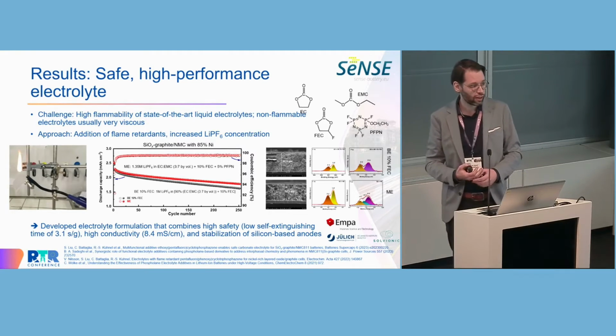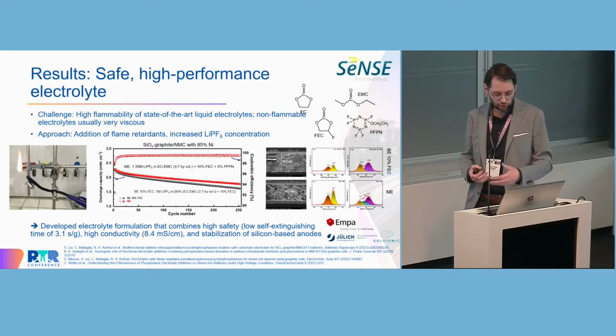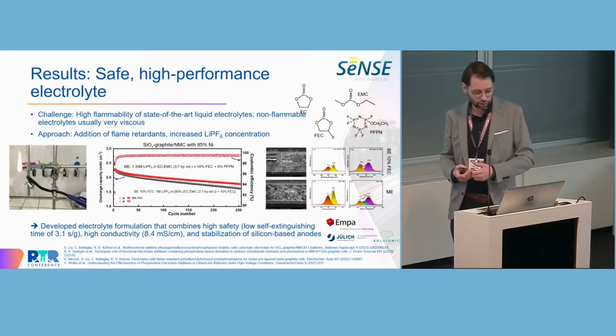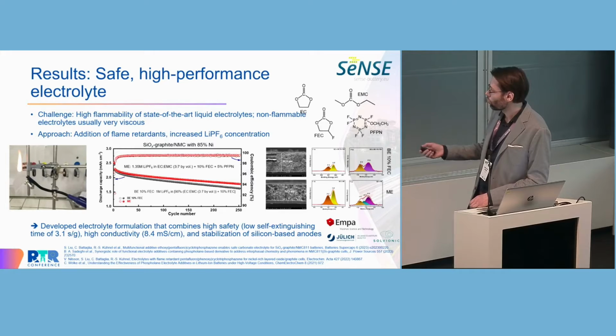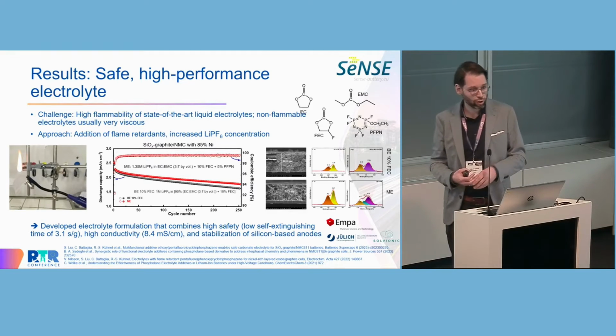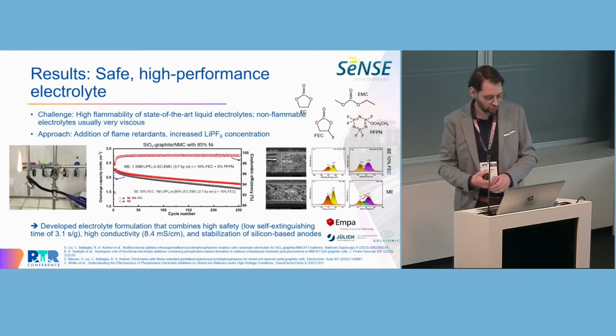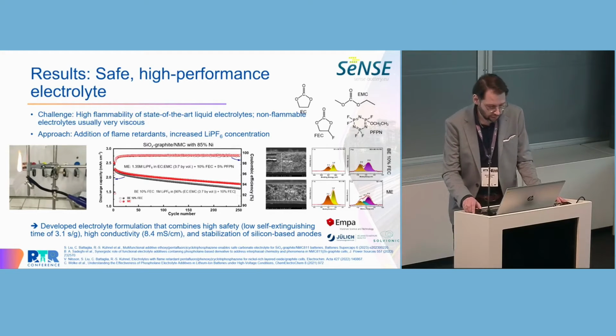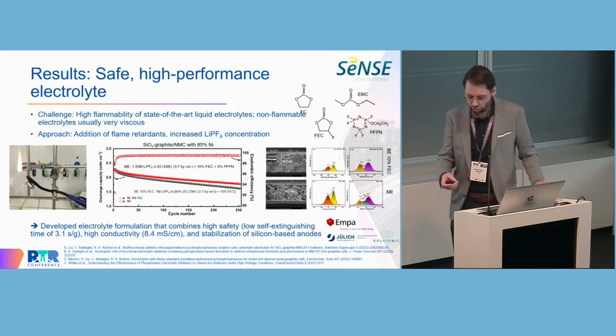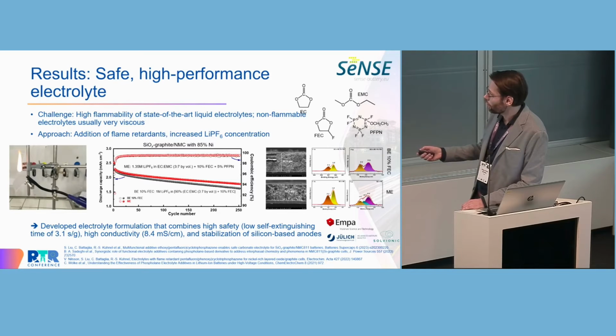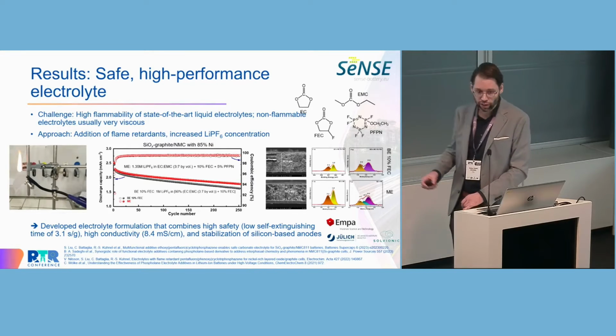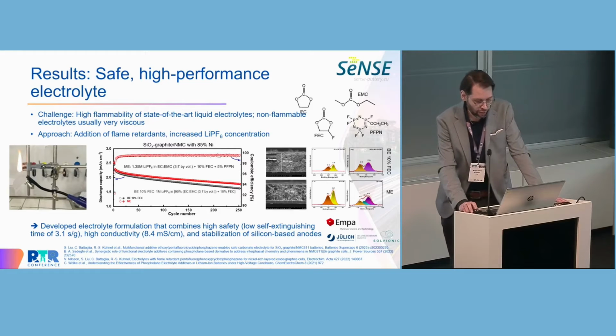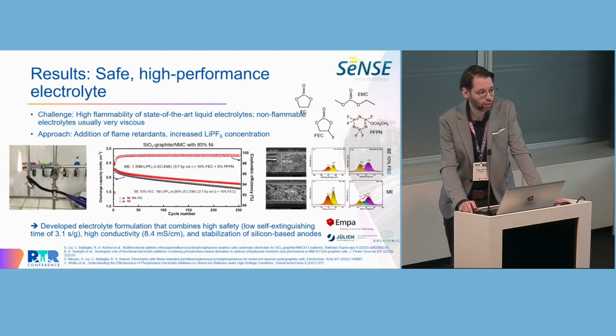We did some post-mortem analysis, and we found that the stabilization mainly takes place on the anode side. We saw that also the composition of this protective layer changes. It becomes richer in lithium fluoride, which is an important SEI component. And we also saw less volume expansion of the anode compared to the baseline electrolyte. And this electrolyte was then upscaled by our project partner Solvionic for the demonstrator pouch cells that we built in this project.